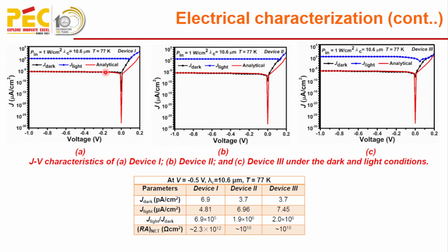And it was found that device 3 has less dark current density as compared to device 1, and device 3 has large photocurrent density as compared to device 1 and device 2, and around 10 to the power 6 enhancement in photocurrent was found compared to the dark current, which is due to the efficient carrier generation at the bilayer graphene and mercury cadmium telluride interface, which is dictated by the built-in electric field present at the hetero interface. Among all, device 3 shows the better performance and better photocurrent density, which is due to the presence of a huge electric field, which is around 180 kilovolt per centimeter at the n active layer and n-plus heterojunction. And such a huge electric field will drift the photogenerated carriers to the electrode, resulting in the net photocurrent through the devices.